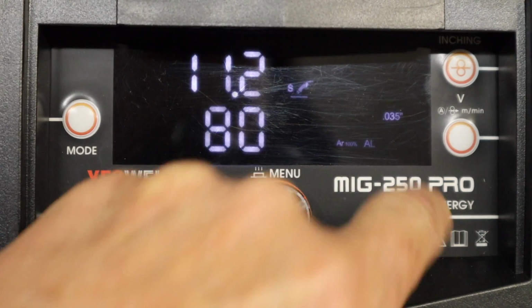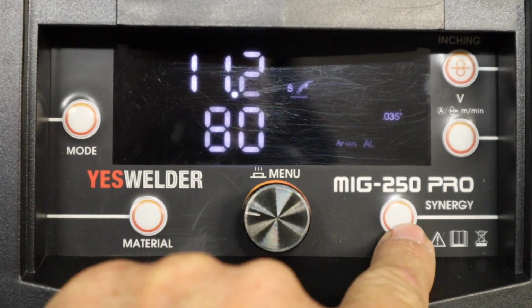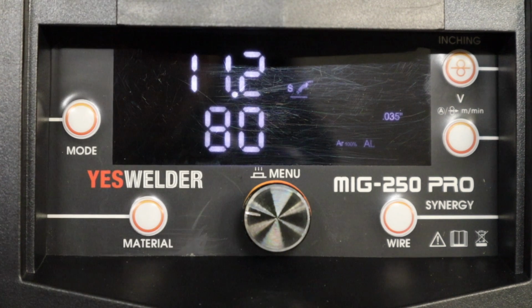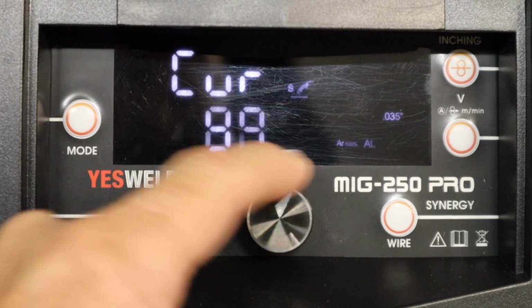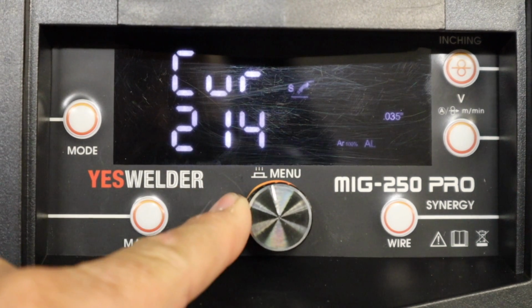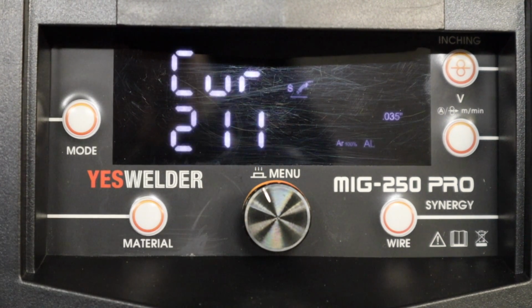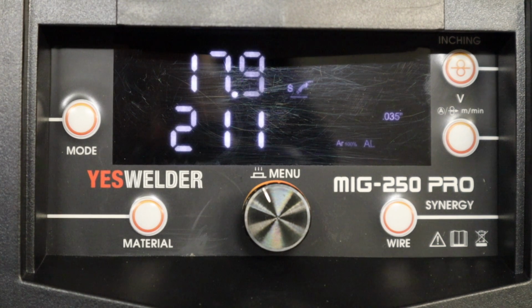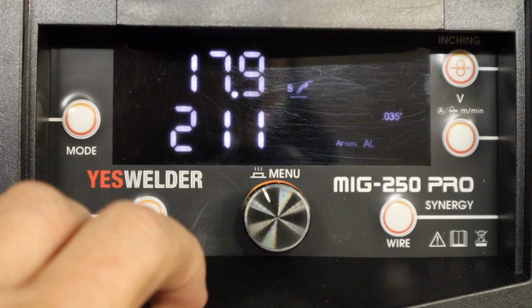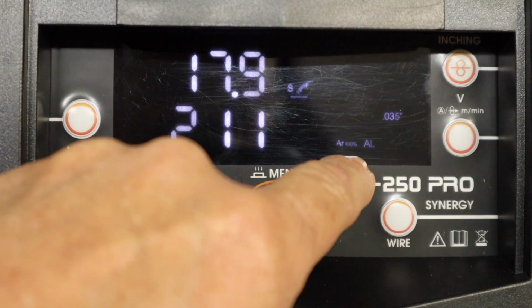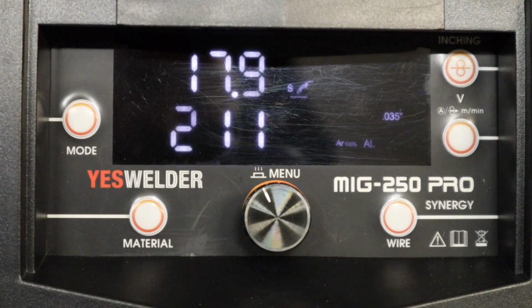I'm using 0.035 wire, so that is set properly. I don't need to adjust that. So I'll be using 1/8 inch material. Using the chart that's provided with the YesWelder MIG 250 Pro, on the bottom of the chart, that's 211 amps for Synergic current, 211. And it's showing 17.9 for the voltage. So we'll try that to start with, and we'll see what that does for us. So I've got 211 set for 1/8 inch aluminum, Synergic, argon 100%, 0.035 wire, using 100% argon shielding gas.